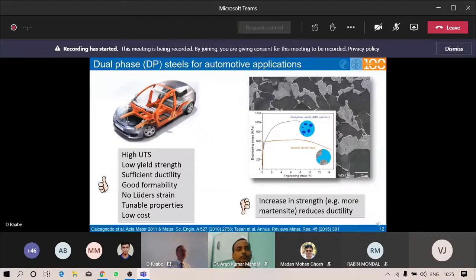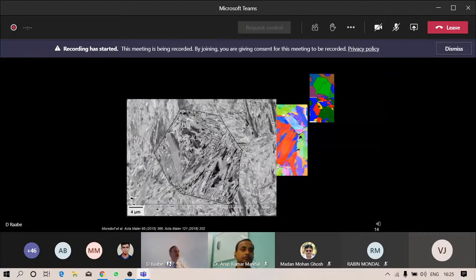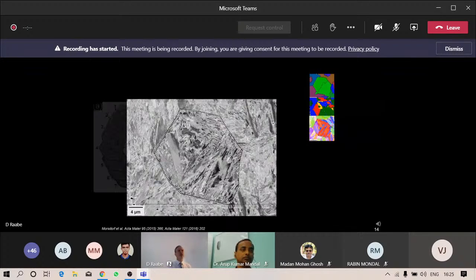Let me zoom into such a martensitic region. You can, by EBSD, measure the former austenite grain from which the martensite was formed, and you can reconstruct the different packages of the martensite. And when you switch, for instance, to the electron channeling contrast imaging mode, you can also reveal the lath substructure, which is very heterogeneous, and you can do that even in 3D when using serial section. I'll show you later more about it.